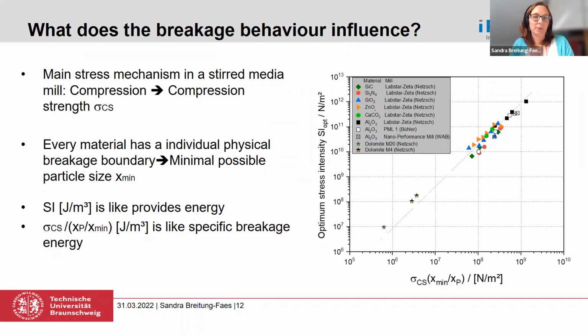And then when I looked this up, I correlated the optimum stress intensity values I get from the origin stress model with this material parameter for different materials and also different mills for my nanogrinding experiments I did. And then all these data points here were achieved. And as you can see, there is a correlation between both of them.